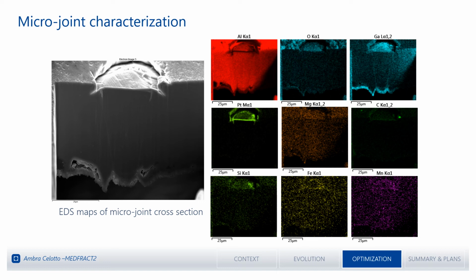EDS analyses were performed also in this cross-section, and still gallium particles were detected in the interface region. So since we can consider that all the possible precautions against the gallium implantation that can develop during the fabrication of the samples were actually taken, now we have to distinguish whether this gallium comes from the fabrication of the samples or actually it comes just from the cross-sectioning procedure. This is our open issue to be assessed and solved.